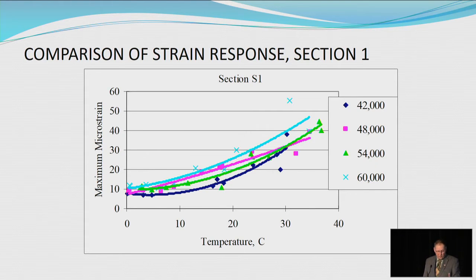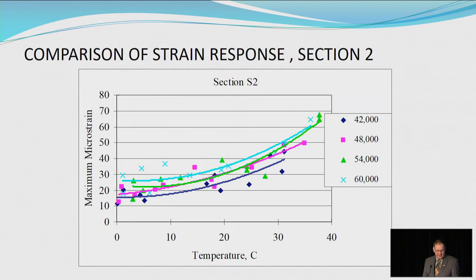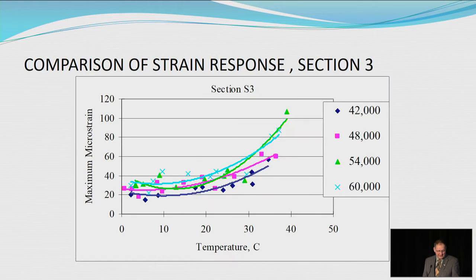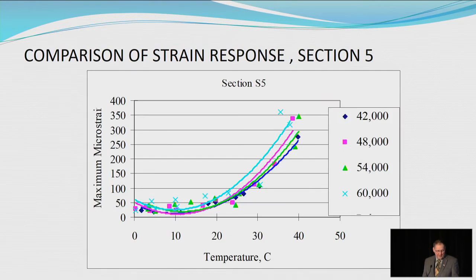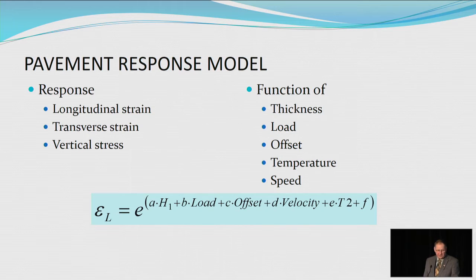And I'm just going to go through quite quickly through the 5 different ones. But there you can see the 4 different loads, the 42, 48, 54, and 60 metric tons for each of the different sections. Section 2 and Section 3 and Section 4. And now the thing to note about Section 5 is all the other ones had been about 100 microstrain and less. And Section 5, you'll see that at a pavement temperature, and this is a mid-depth temperature for the pavement, it's operating in the 250 to 350 microstrain area, so substantially higher microstrains.